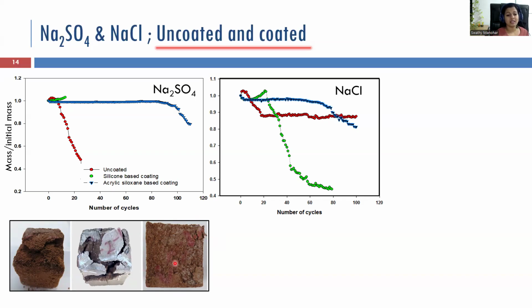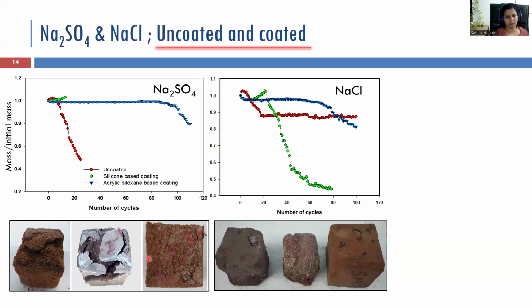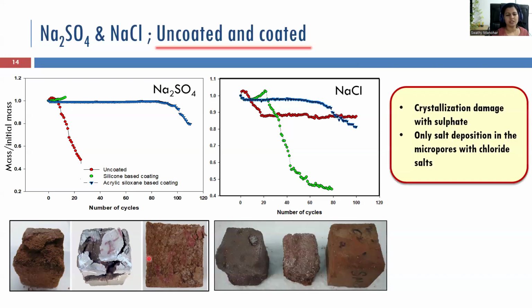So if we are giving a right coating which is compatible to particular material and salt, then it would perform better in long term. Same is the case with sodium chloride as well. So the takeaways are: with sulfate, it is a crystallization damage. But in case of sodium chloride, only salt deposition happens inside the material in the micropores.